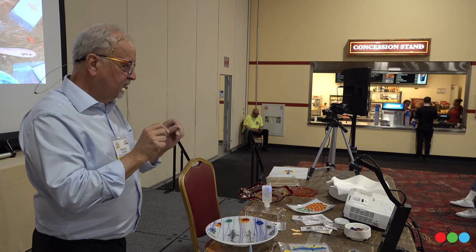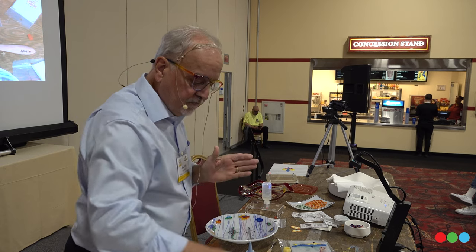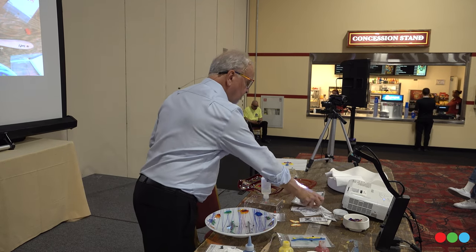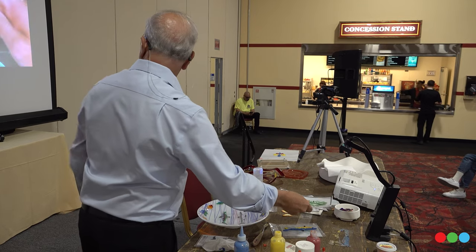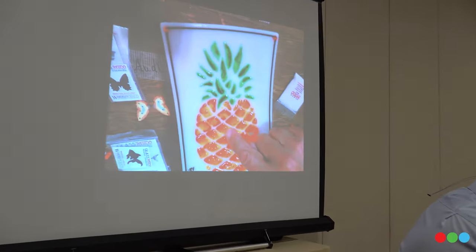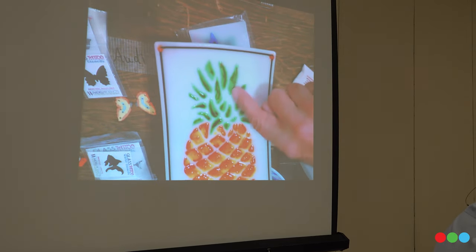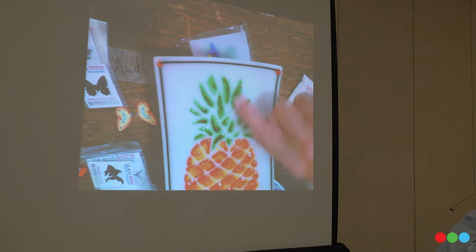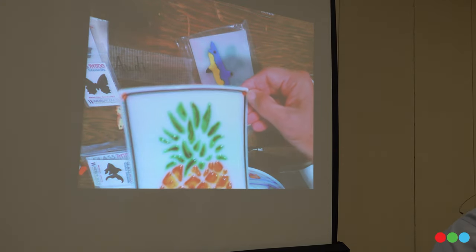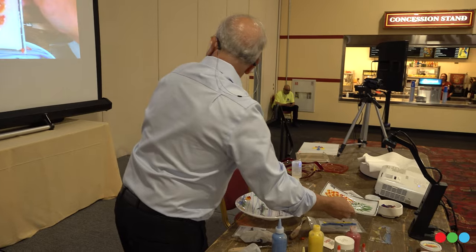Very many of them burn off at five or six hundred degrees, and then that's the point when the powder relaxes and you don't get as sharp, clean edges. I was really looking for sharp, clean edges. That's important to me because when you look at this thing, it's pretty remarkable — that entire design is done in one shot. I used yellow, orange, and red in each one of those little cavities; each cavity is part of the stencil. And here I used three different greens — pale green, darker green, and a mid green. And the border is just a spaghetti stringer with a dab of red at the end to hold the stringers in place until I fired it.